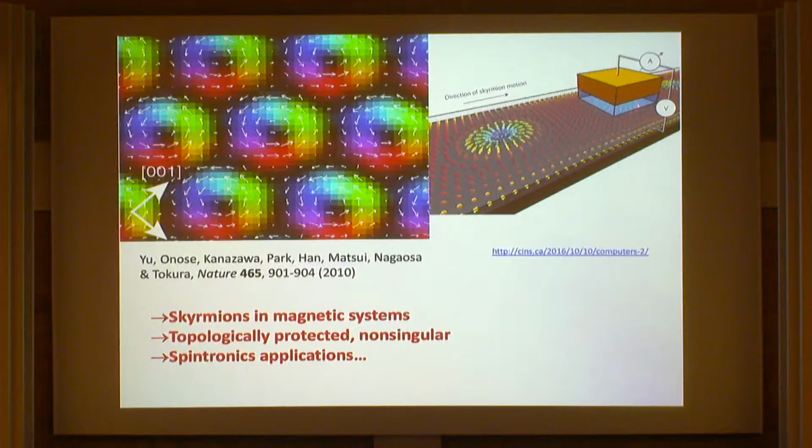And then when you need to read and write information, you would run them on such a racetrack and read and write information. So the size of these magnetic Skyrmions can be sub 10 nanometers, and so this would allow quite dense data storage, also because with racetrack memories you would not have to be confined to 2 dimensions, but could also go to the third dimension and store them elsewhere, not necessarily within these racetracks.